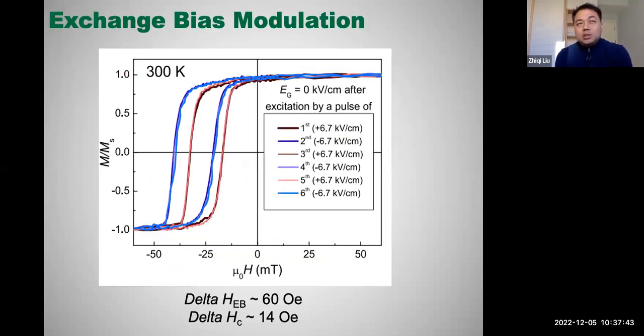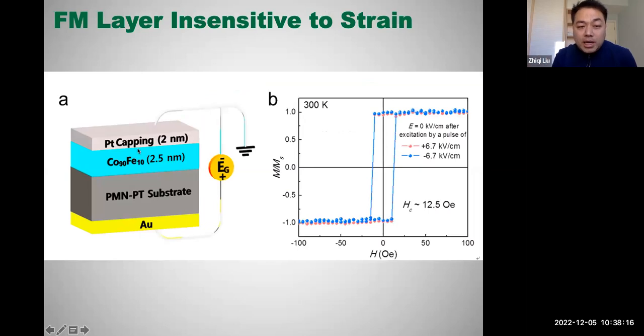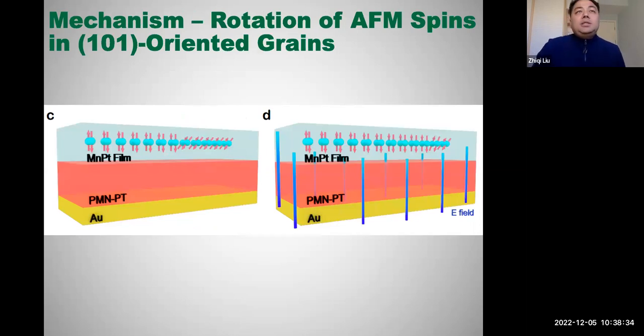We continued to perform other experiments to study what happens when we apply an electric field to the piezoelectric PMN-PT. We grew a cobalt iron layer on top of the manganese platinum layer, so it generates an exchange bias at the interface. We found that for different resistance states, the exchange bias was reversibly modulated by the electric field or piezoelectric strain. However, the thin ferromagnetic layer of cobalt iron, which is only 2.5 nanometers thick, is not sensitive to the strain at this strain range. So we conclude that the variation in the exchange bias is due to the modulation of the antiferromagnetic spins by piezoelectric strain. That's why we have this kind of cartoon image to show how the antiferromagnetic spins could be changed by the piezoelectric strain.